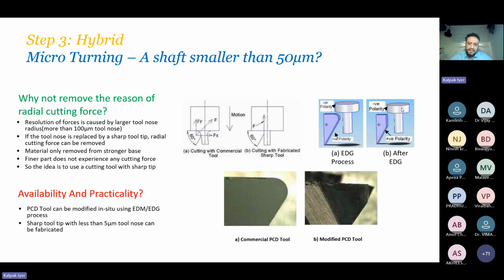In wire EDM, the wire is the anode, positive polarity, and the polycrystalline diamond has negative polarity. Polycrystalline diamond can be EDM machined because it is usually sintered with cobalt or some other sintering binding agent. So it was machined on the same setup. Basically, we turned up to 100 micron, took that turned shaft, put it in the EDM tank, made the spindle into an EDM head, and used wire EDG to make this smaller tool.